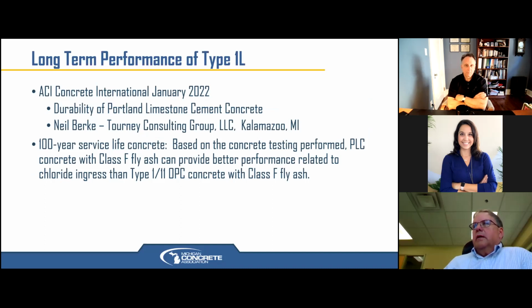Talk about long-term performance. I don't know if many of you are aware, but Tourney Consulting Group out of Kalamazoo is a very high-tech testing firm, and they get involved in pretty high-level stuff around the country. There was a project in Oregon similar to the Gordie Howe Bridge. They wanted to have a 100-year design service life of concrete. So they came to Tourney Consulting Group and said, run some tests to show us that our type 1L cement will be a 100-year service life concrete. And they did that. In those cases, they're using a type F fly ash, but their results showed that the type 1L cement was going to perform probably slightly better than the type 1 would have. So they've confirmed with their testing that long-term, we should expect to see very good performance with this type 1L cement.